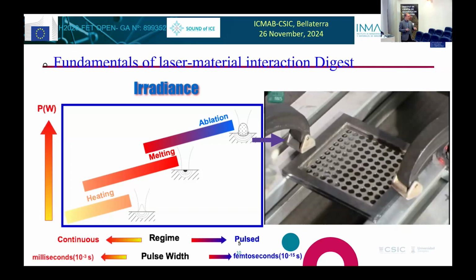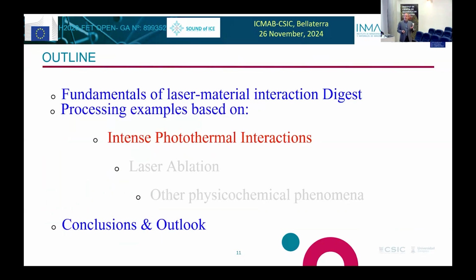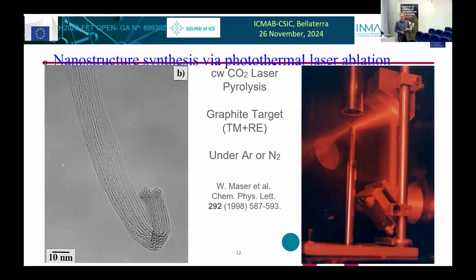What this means is that if you do ablation, it's a much more aggressive process than just melting. And it starts to go out of equilibrium. Melting is almost an equilibrium process in this case. And ablation is out of equilibrium, and it's very aggressive, very intense. So when we have intense photothermal interactions, for example, we can do this. We can transform graphite targets which have embedded, for example, transition metal and a rare earth like nickel and yttrium. You can transform it above 3,000 degrees because this is intensely photothermal with a CO2 laser. It's transforming this graphite target into single wall carbon nanotubes, as you see here.